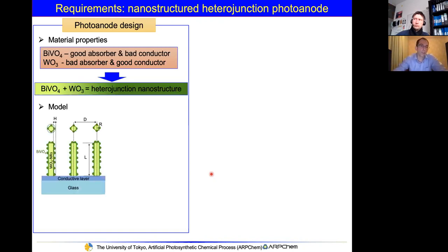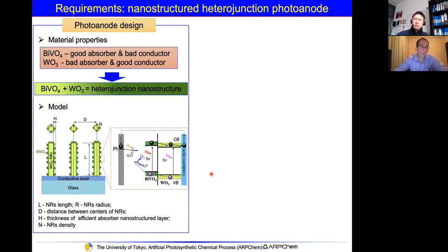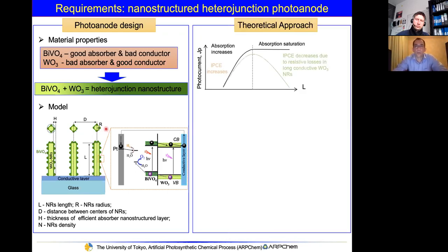Okay, so this is the model. Here H is the thickness of the bismuth vanadate material, D is the distance between the centers of the nanorods, L is the length of the nanorod, and R is the radius of the nanorod. From the theoretical approach, we know that if the thickness of the material increases, absorption also increases. Once we reach a certain thickness, the absorption saturates, so we don't need to deposit more material because we already reach full absorption.